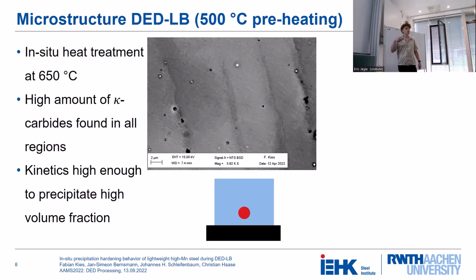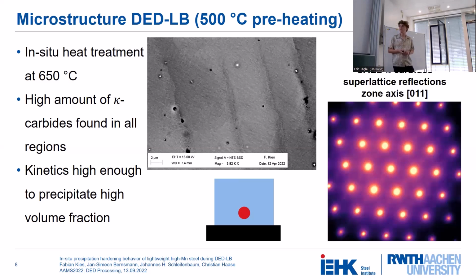And if you take a look at the microstructure at the bottom of the sample, which has seen a much higher amount of heat, you can even see high amounts of kappa carbides in the dendrite cores. So the kinetics are high enough to precipitate the kappa carbides. And just to confirm that these are really kappa carbides, this is a TEM measurement with a SAD pattern in [011] zone axis. So the large spots are from the FCC phase, and in between, these faint spots are the superlattice reflections of the kappa carbide phase. So it was possible to precipitate the kappa carbides during the DED processing.